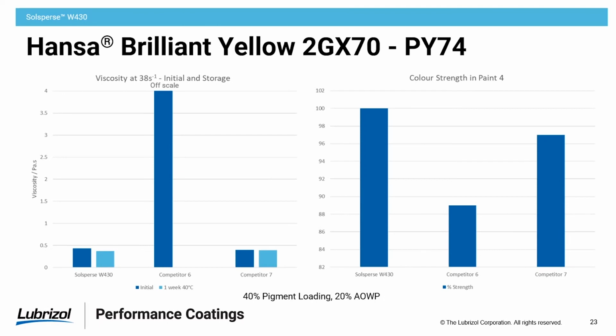And then finally, a high-strength organic yellow. When we're talking about yellow pigments that are used quite a bit in architectural systems, this is one of the standards. And the anchor system on the W430 is ideal for a pigment like this. Right up there with maybe our closest competitor, which we list here as competitor number 7, in terms of viscosity, stability, color strength. At the deep level it is actually a little bit better, but we perform well. And again, this is another pigment system which can be quite challenging to get a 40% pigment loading.